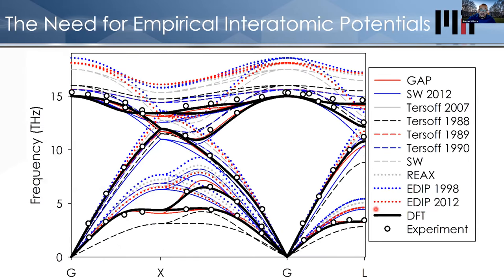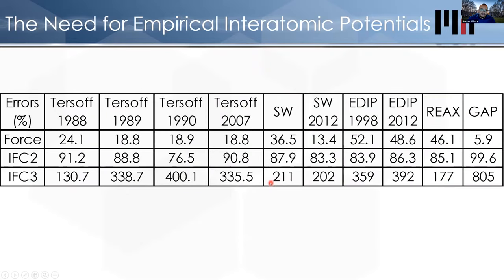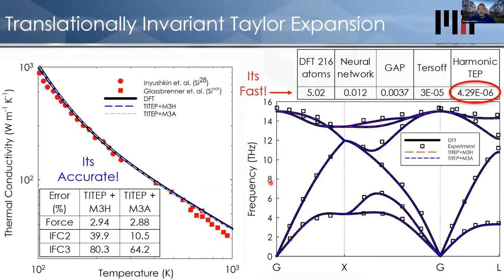Here's now the problem with a lot of those models I showed previously. The experiments are here. DFT agrees with the experiments, but you see all these models are not able to describe the frequencies of the modes correctly. They're all over the map. When you look at the errors in the forces, they're very significant. I'll move faster here. In short, we think we have a pretty good solution for this problem. Again, we're about a million times faster than doing it with DFT, and we're spot on in terms of describing thermal conductivity and the dispersion of frequencies.